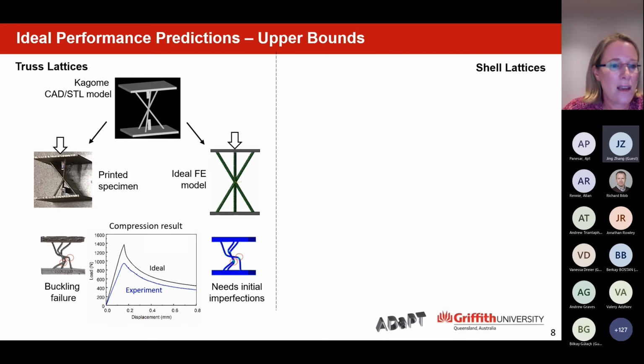We generally see that the experiment gives a lower stiffness and a lower stress. And also in this case, the peak load value is actually much smoother for the experiment than it is for the ideal model. I also want to point out this ideal finite element model actually doesn't buckle by itself. So for those of you that know buckling, nonlinear buckling analysis for numerical simulation, you might know that ideal structures need a bit of, don't want to say push, but you need to introduce a bit of an imperfection to actually make this buckle.